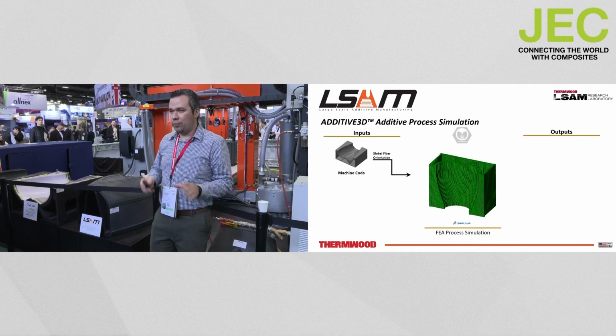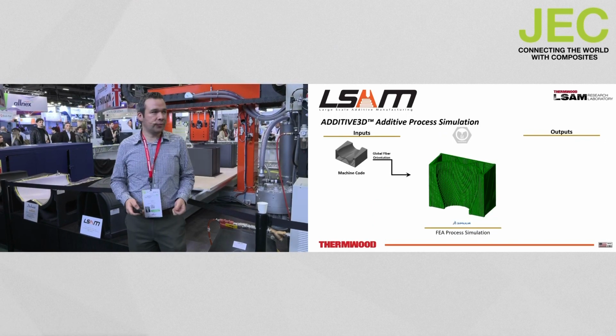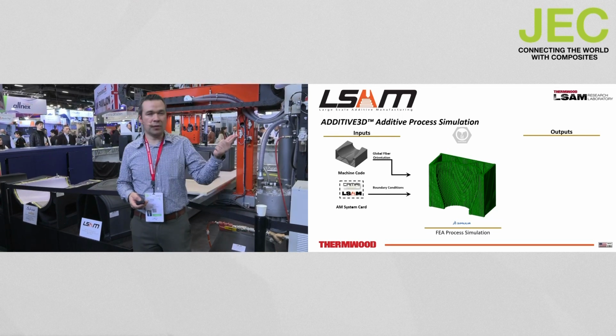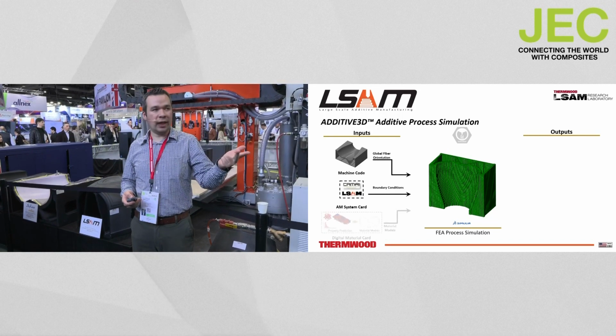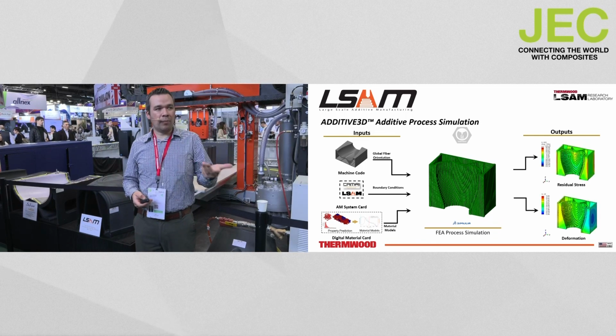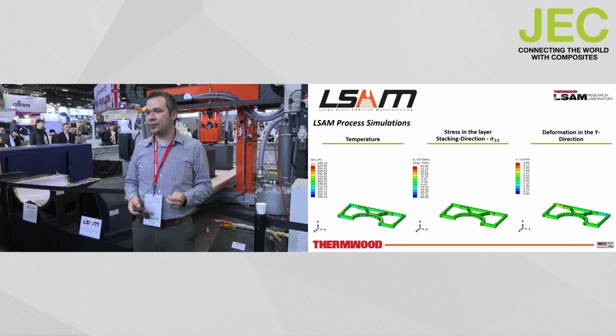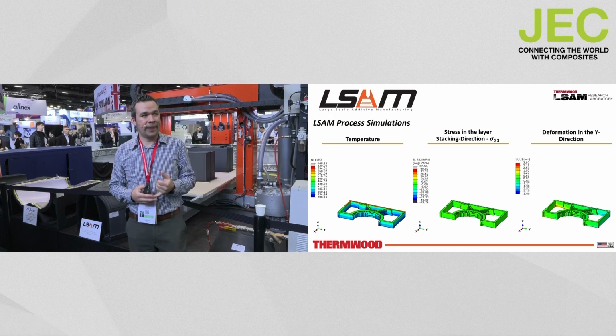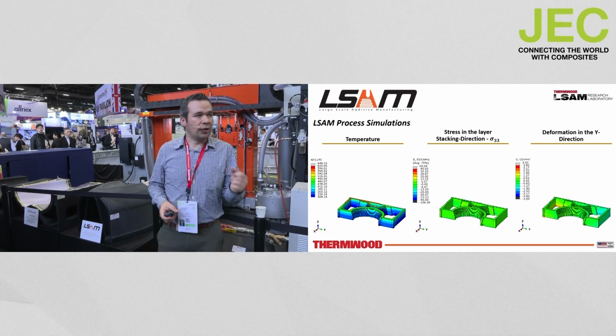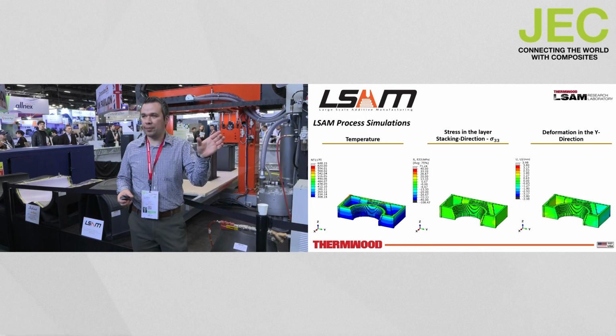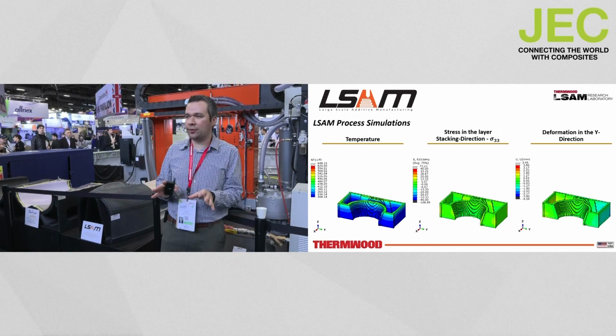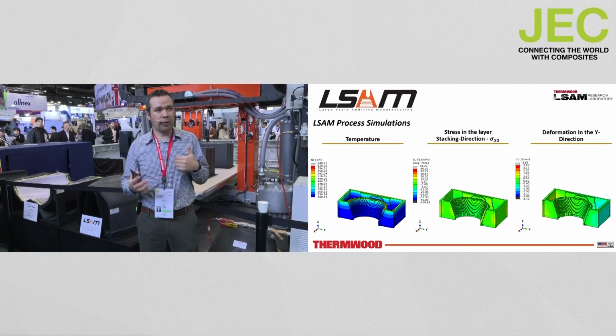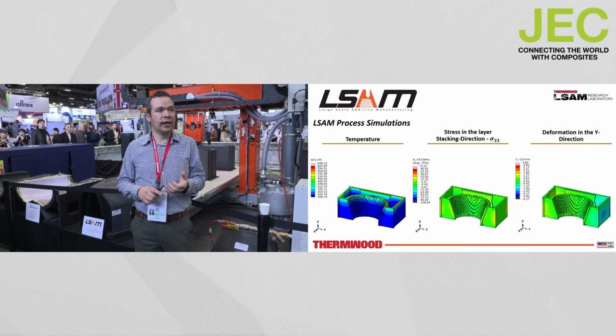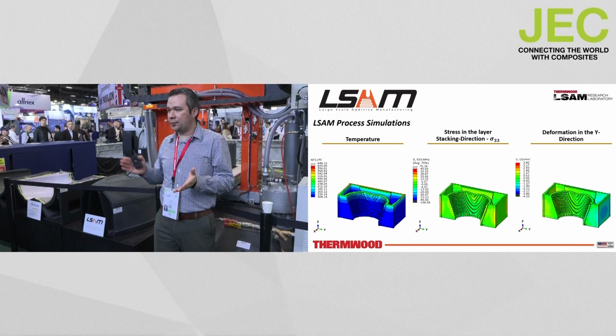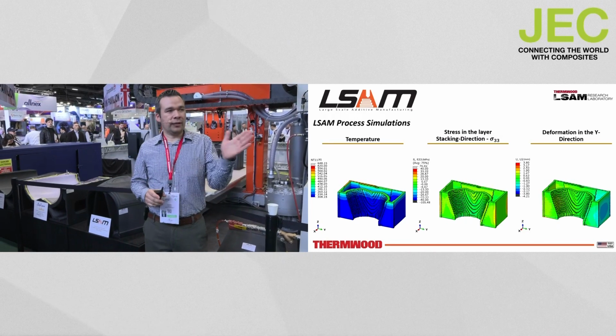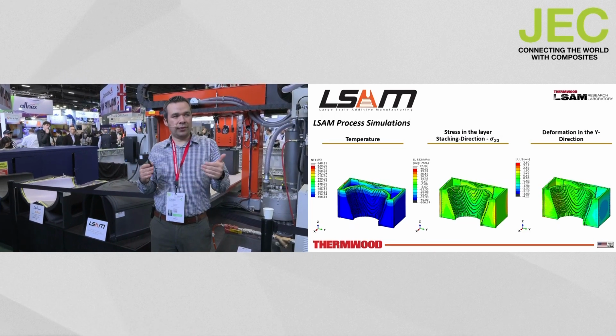Just to walk you briefly through one of the examples of a process simulation. To simulate the print process, as I mentioned, within the machine code, we need a machine card and we need a material card. And we can predict, for example, residual stresses, deformations, and temperature history. You can see here on your left-hand side the evolution of temperature throughout the print process. So it's a highly non-isothermal process. And some of those temperature gradients obviously lead to stresses. In the middle, you can see stresses transverse to the print direction. And then on the right-hand side, we're looking at the deformation in the y direction.